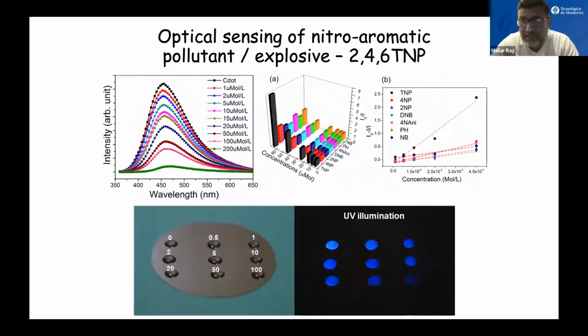I will just show you here a few basic preliminary applications that we could do in our lab using these amorphous carbon nanostructures. The first one is a simple thing. It was detection of a nitroaromatic. Of course, we cannot work with TNT in the lab, so we work with TNP, that is trinitrophenol. And we could see that these amorphous carbon dots, by suitable tailoring of the surface species, and we needed a little bit of chemistry in that, so I took help of colleagues working in chemistry to attach suitable surface species which are very sensitive and can specifically attach to TNP, could extremely sensitively and selectively detect TNP, and one of the best, if not the best, that have ever been recorded. And the mechanism of detection is simply based on quenching of the luminescence intensity.